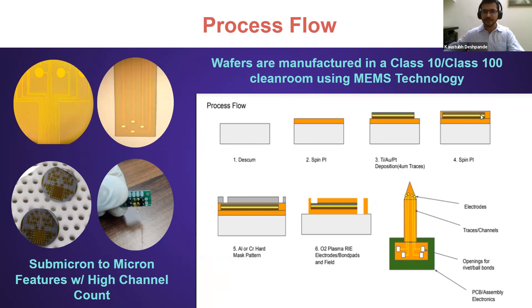The next step is then to spin coat a second layer of polyimide, which acts as a second layer of insulation on the top. And then we use oxygen plasma etching to open electrodes. So the electrodes are essentially open on the top part of the polyimide, and then the outline is etched off to singulate the devices. So on the bottom right, you see the devices on the wafers being singulated, and on the top right, you can see the electrodes.